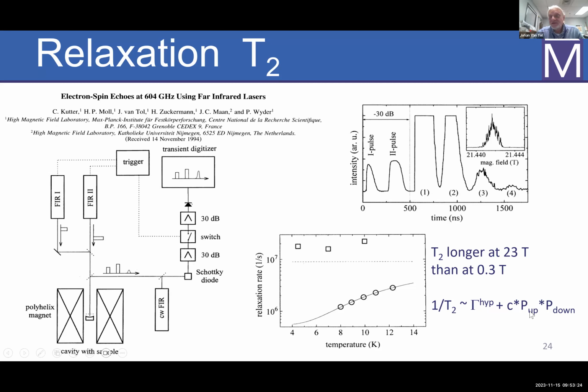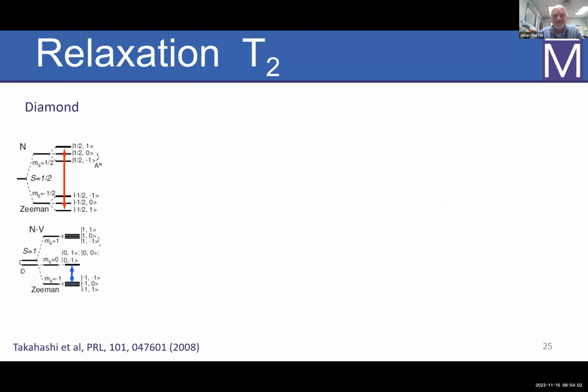So typically, the polarization of your upspin is 1/2, and your polarization of your downspin is 1/2 at high temperatures or low frequencies. So that comes to about 1/4. But if you have 1% polarization, then this number gets much smaller, over kind of a 99% polarization, this number gets really much smaller, and you start to see that. So a simple model: the number of pairs of up and down spins determines your T2 in this concentrated system.